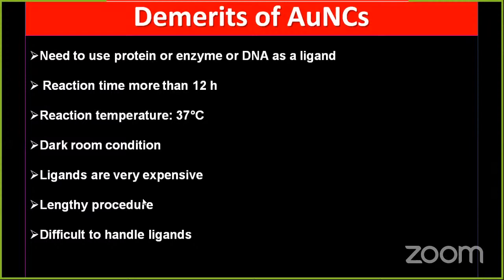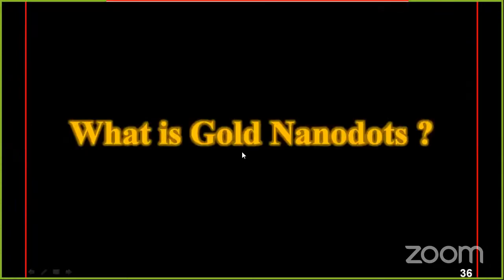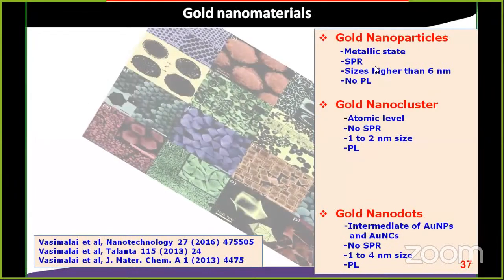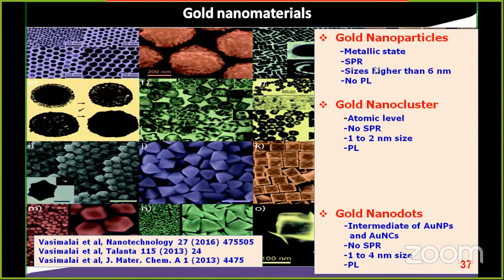Demerits of this one I already discussed: dark room conditions, very expensive ligand, lengthy procedure, difficult to handle the ligand, because people are taking DNA, reaction time 12 hours, 37 degrees needed to heat it. Then gold nanodot is a new class of fluorescent gold materials. It is an intermediate between gold nanoparticles and gold nanoclusters: 1 to 4 nanometer size, with no surface plasmon resonance. So it doesn't have an SPR band.